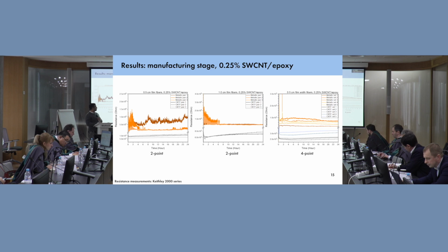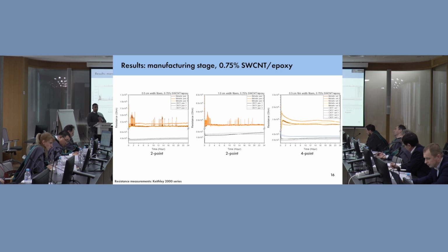But for our metallic electrodes, same basic response. But even here in this experimental batch, for our 4-point, we still see some spikes show up, just an artifact of this experimentation. So for our most conductive or least resistive nanocomposites, we again start to see similar behavior. So across the board, we see matching of our carbon nanotube fiber results. We see that our metallic electrodes are providing some form of contact resistance, either in the form of noise or in the form of magnitudinal error.